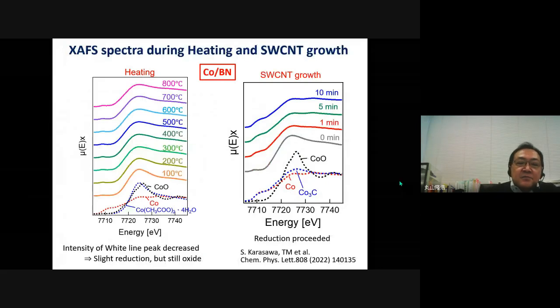These show XAFS spectra during heating to the growth temperature of 800 degrees C and during carbon nanotube growth. As the temperature rises, the peak at the absorption edge decreased. This indicates reduction of the cobalt catalyst. After ethanol supply for single-wall carbon nanotube growth, the spectral shape changed a little, and the peak intensity decreased. Next slide, please.